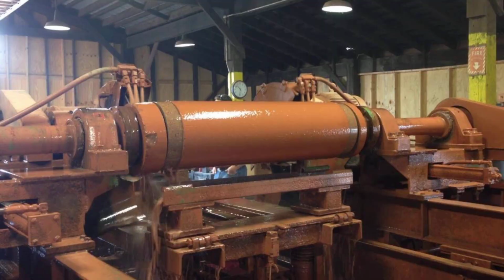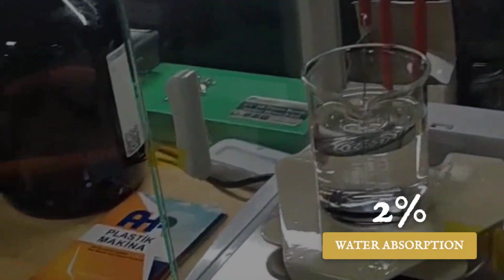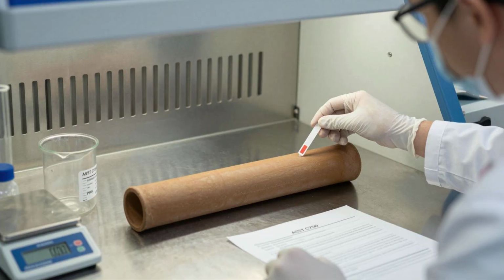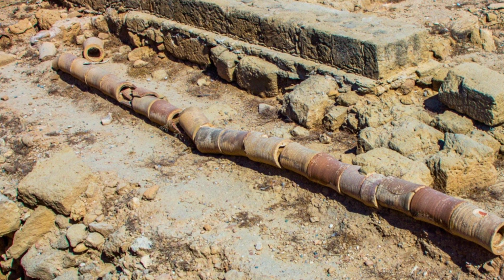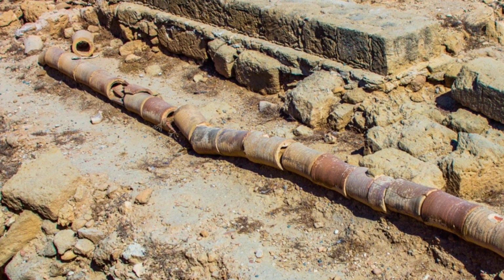It is controlled by modern tunnel kilns that hold temperature to within 5 degrees, ensuring every section vitrifies evenly from end to end. The result is a ceramic so dense it absorbs less than 2% water by weight, with a surface that shrugs off acids, salts, and sewer gases. Laboratory tests confirm what the ancients intuited by trial and error.